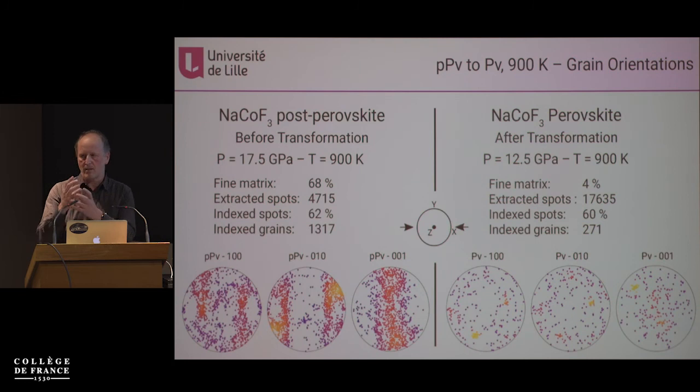And I think there's a question of what is a grain anyway. A grain you see in diffraction and a grain you see in electron microscopy is not the same thing. In diffraction, you see orientation space. And so I think here we see many domains very close to each other in orientation, but it's probably just one grain. Or just a few grains, not so many.